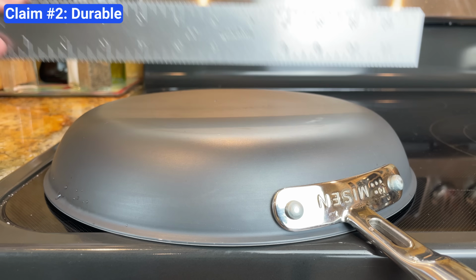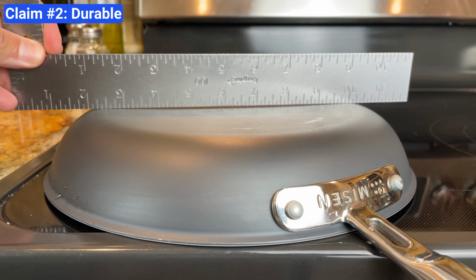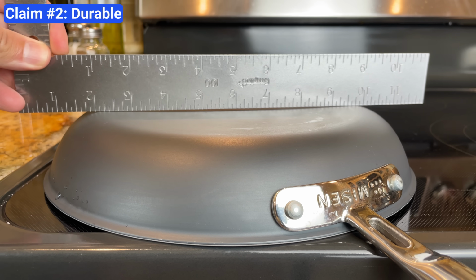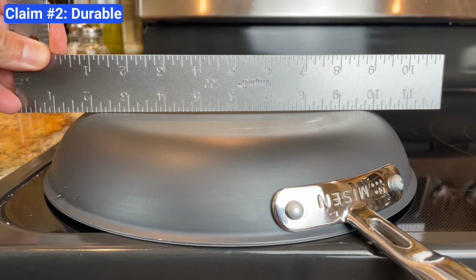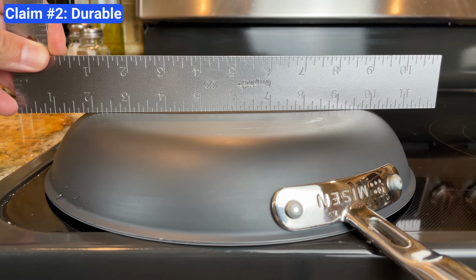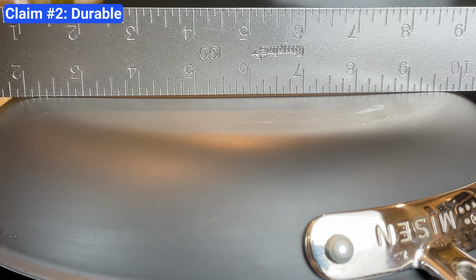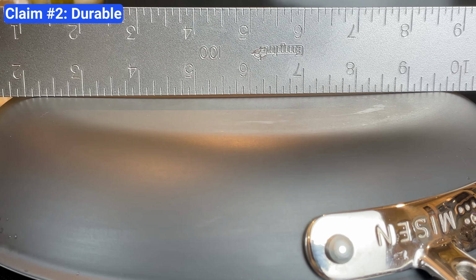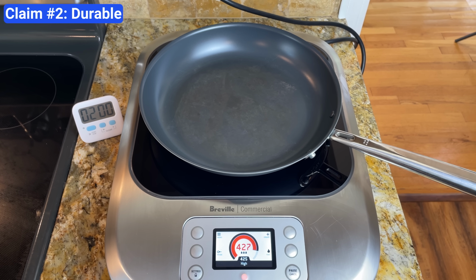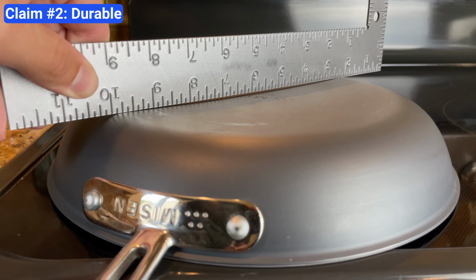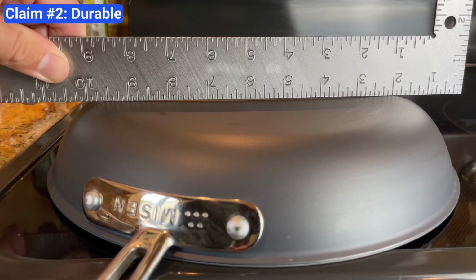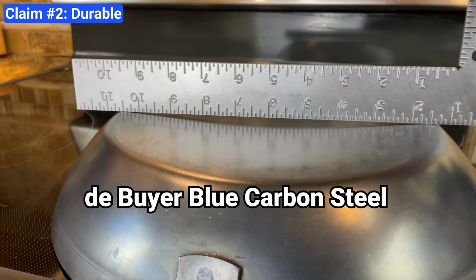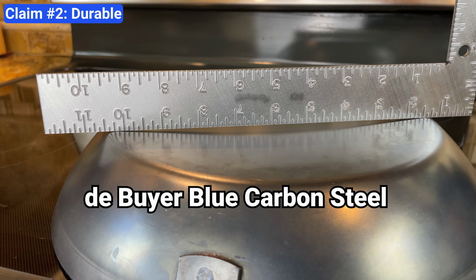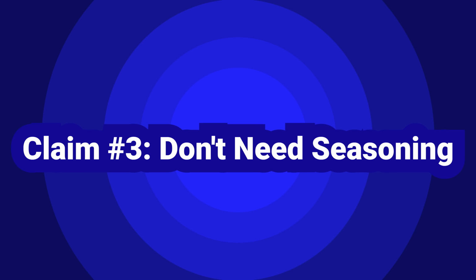Because the Misen pan has an aluminum core, in theory, it should spread heat more evenly and resist that stress. To test that, I measured how flat the bottom was before and after heating the pan to 425 degrees Fahrenheit for 2 minutes on an induction cooktop. The pan started out slightly concave, which is normal. Manufacturers often build that in to account for expansion. After heating, the shape didn't change at all. I ran the same test on several other carbon steel pans, and not all of them held their shape.